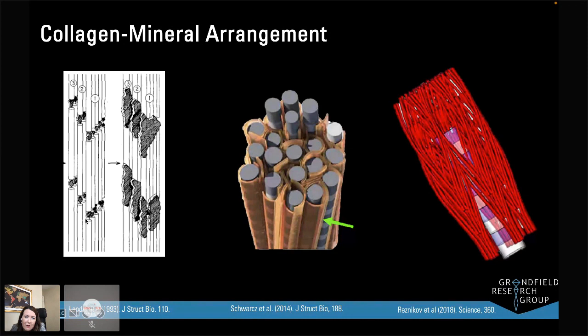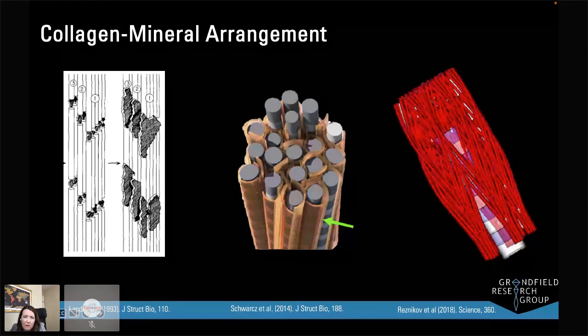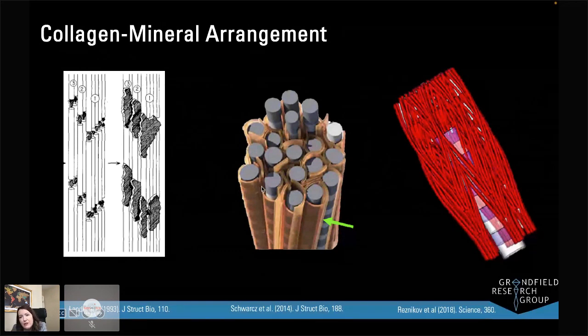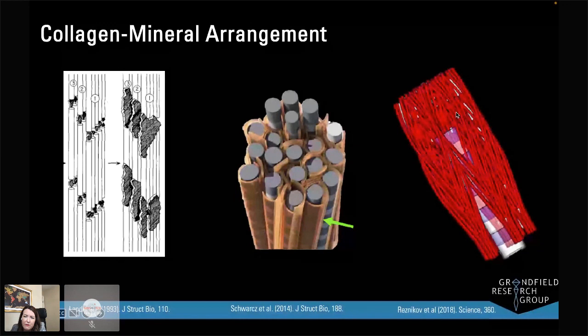shows that the mineral phase begins inside this gap zone between collagen fibrils and nucleates outwards. A model by my colleague at McMaster shows that instead the mineral takes the form of curved plates wrapping around the collagen fibrils. And just a few years ago, a model by Natalie Reznikov, who's now at McGill University, shows that the mineral phase takes place in a cross-fibrillar mineralization of slightly different shaped particles.